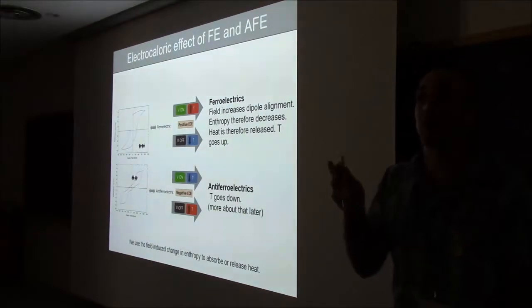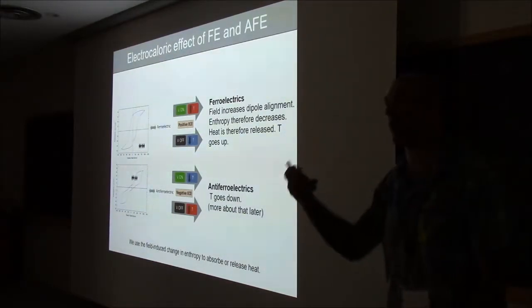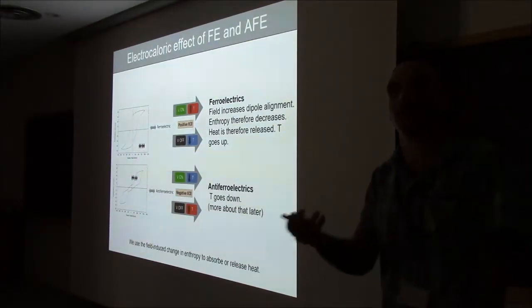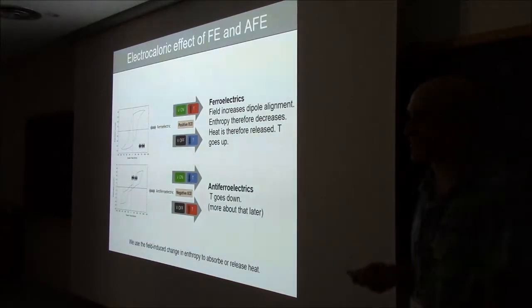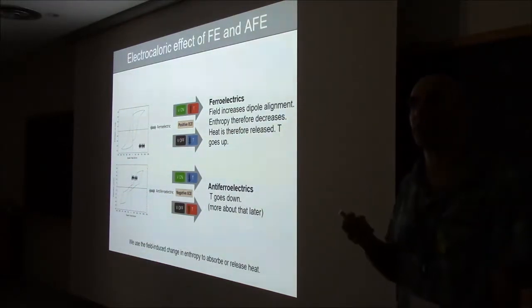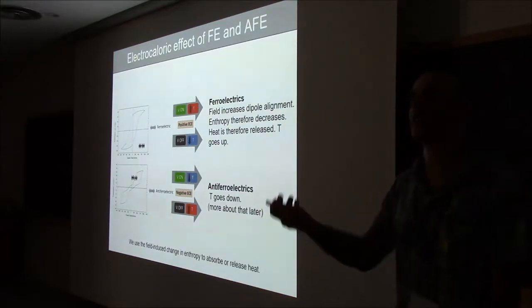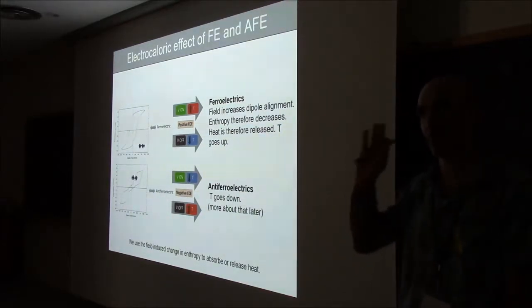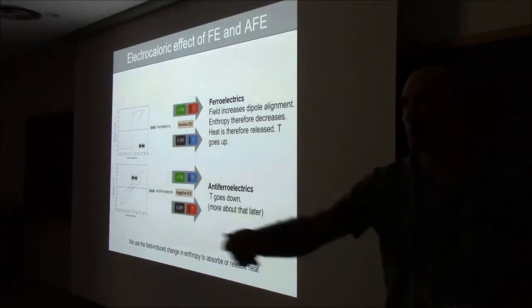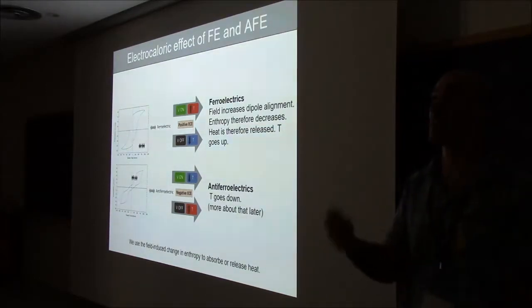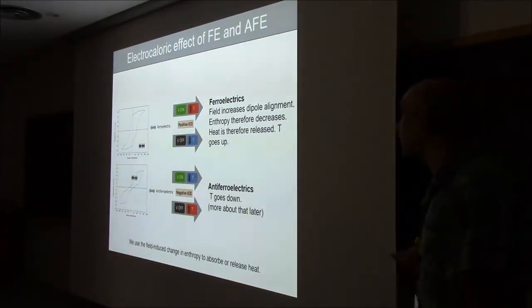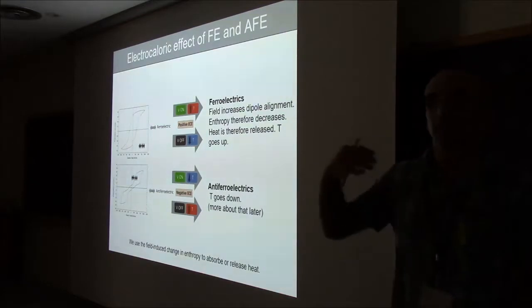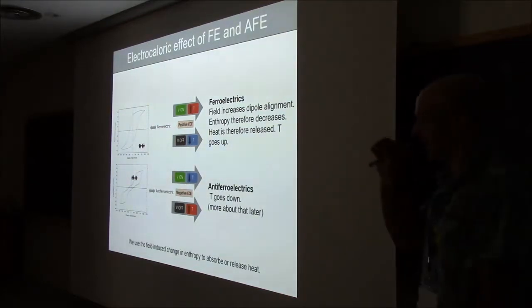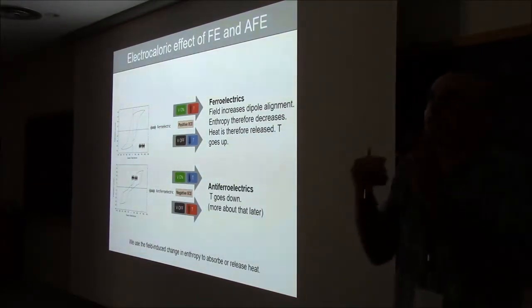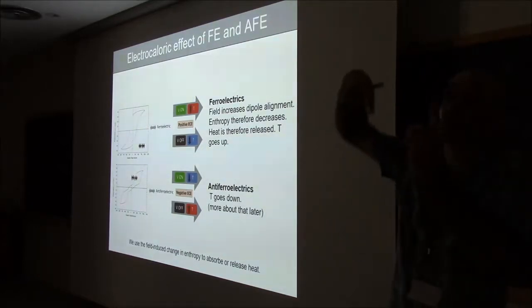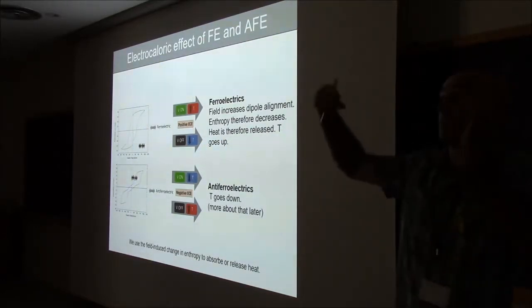A cool thing that happens in anti-ferroelectrics is that you get an anti-electrocaloric effect, which is that when you apply your voltage, your material, instead of getting hotter, it gets colder. And that's pretty funky when you think about it. I'm putting energy into my system, I'm applying a voltage, and my system is getting colder. And the reason why that happens is debatable, but the bottom line is that somehow you must be increasing the entropy.